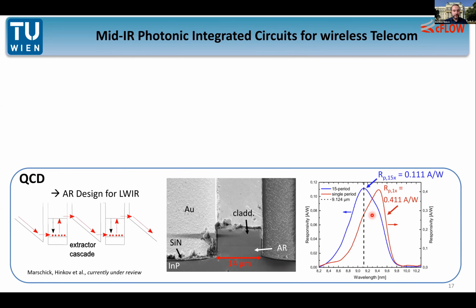we address here. First of all, we address the detectors, where we develop new detectors in the project, which have higher responsivity, significantly higher than those record values in this wavelength range. And we can use them, of course, for direct substitution in the experiment to shine light on the facet of this detector. So this is a dielectric waveguide now, just to stress it, to shine light on it and to make the detection. And this should work very nicely. We're going to do this experiment now, but there's one problem.